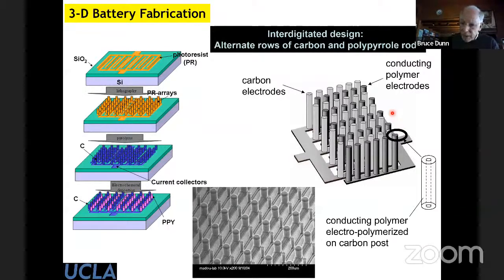And so what we did is that on one set of electrodes, we preferentially electrodeposited a conducting polymer, polypyrrole, which could serve as an anode material. It's not a great anode, but at least you could prove the concept of this. And at the end, here's what you wind up with. It's a beautiful array, almost as if it's the way that you drew it. It's thicker because of the polypyrrole that you need in order to match the capacity of the carbon, or at least come close to that. And then you could see the lines of carbon on the lines of the polypyrrole arrays.